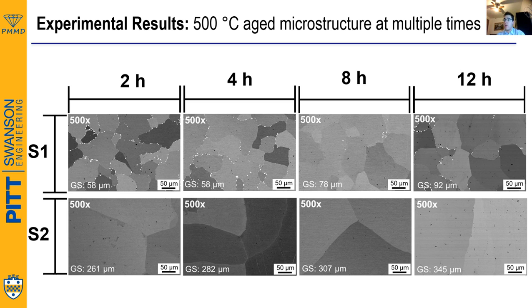Now, here you have a third set of backscatter SEM images. These correspond to the microstructure of S1 and S2 aged at 500 degrees C at multiple aging times. We clearly see here that the pinning of grain boundaries in S1 provides this sample with a grain size that is about 3 times smaller than the reported grain size of S2. Moreover, S1 keeps a relatively constant grain size, and this is mainly because of L21 pinning the grain boundaries, refusing to dissolve even after 12 hours of aging.